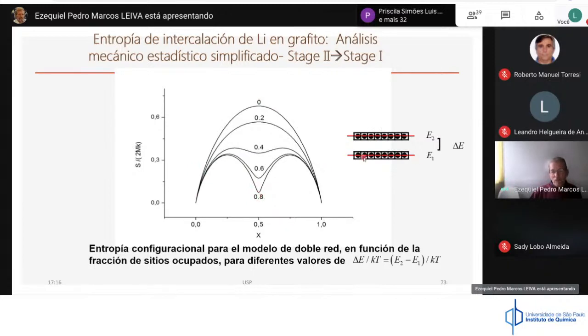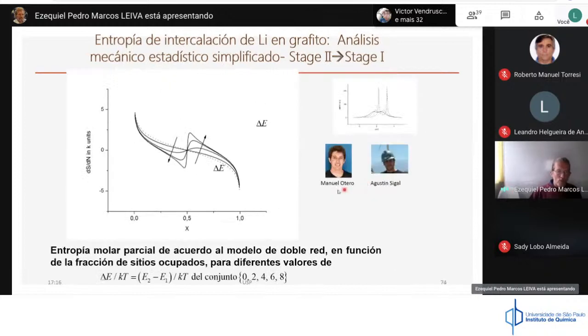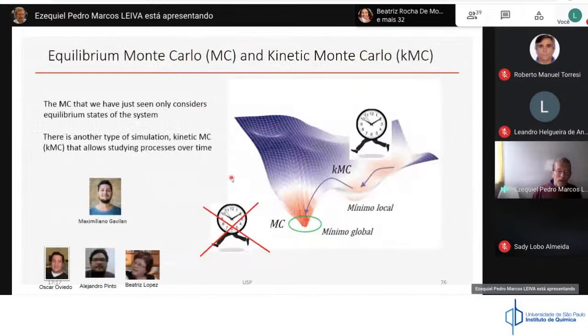Why? Because you start filling this layer here, and finally, when you go on filling this layer, at some point the entropy decreases because you have no more configurations to find. But as soon as you start to fill the other lattice here, you get an increase again in the entropy. This is a very simple model that we use to understand what the complicated computer simulation shows. And this is the result of the statistical mechanical model, where you see that this step in the partial molar entropy can be understood in a much simpler way.